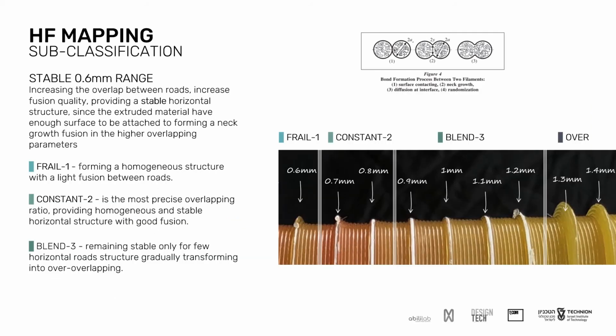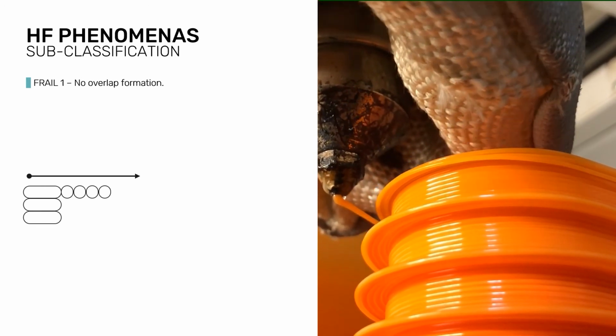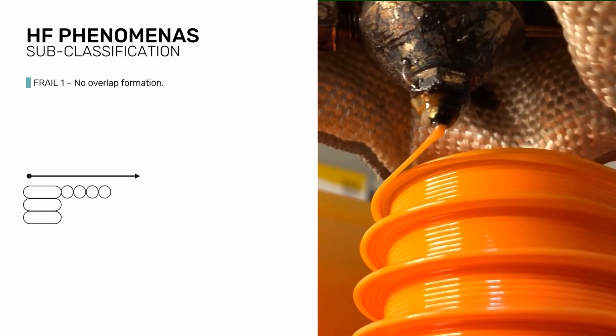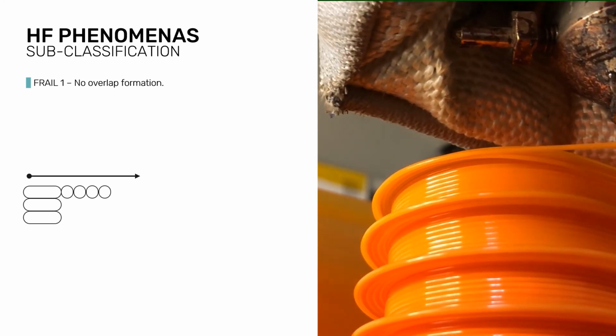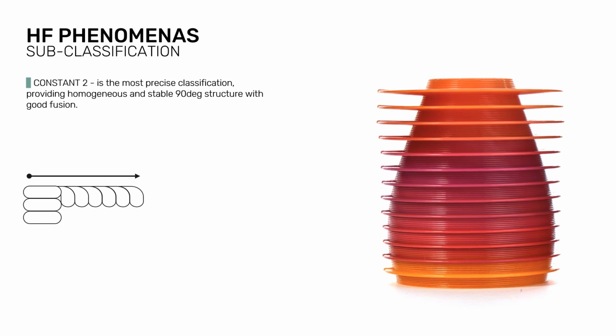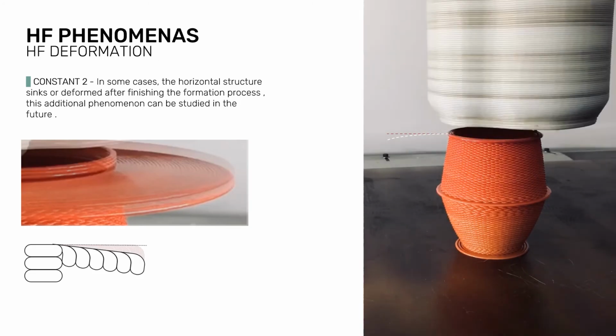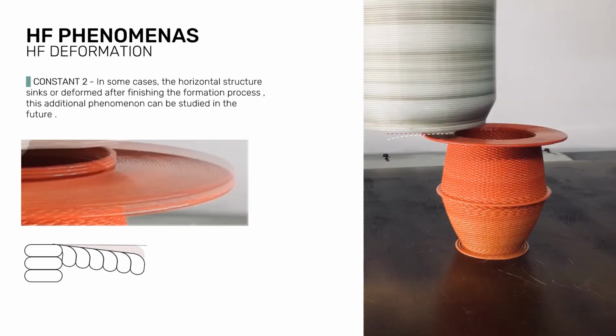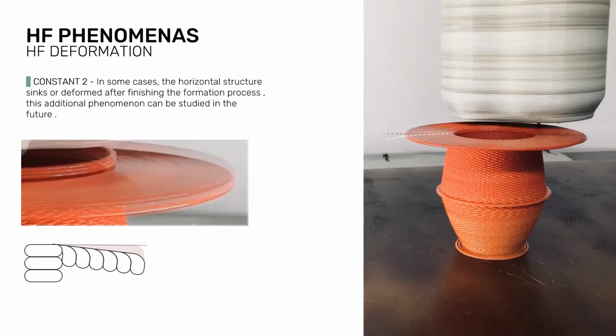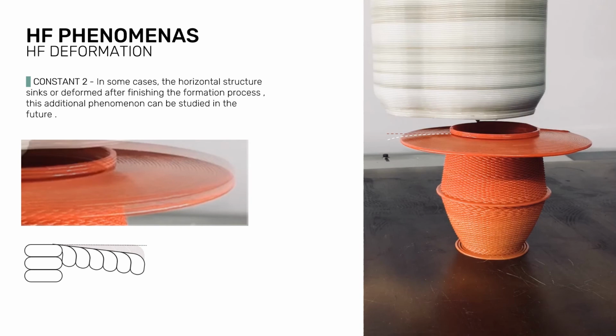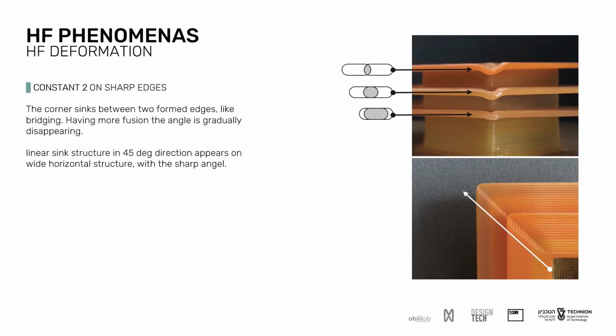Different fusion quality can be seen by the white marks that appear after detaching the horizontal rods. Frail, for example, has the lowest fusion and can be detached almost without harming the artifact, and in some cases forms without any contact or overlap. Constant is the most precise classification, providing a homogeneous and stable 90-degree structure with a good fusion. In some cases, the horizontal structure sinks or deforms after finishing the formation process. Although good fusion appears at the straight line and a rounded line, material sinks at the sharp edges.